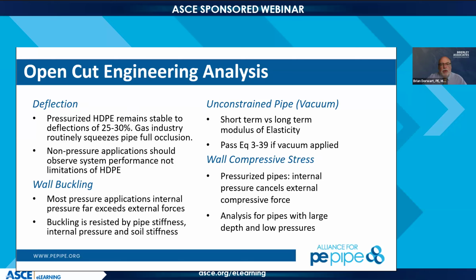The important part of this is if you have bad backfill, you forget to compact it, which sometimes happens, that material is going to start over time loading up on your pipe and your ovalization will start occurring more in a long term. Is that a big deal or not? No, because eventually it's going to stabilize because it's, again, a granular material. But soil is very important, and that's where the modulus E prime comes in.